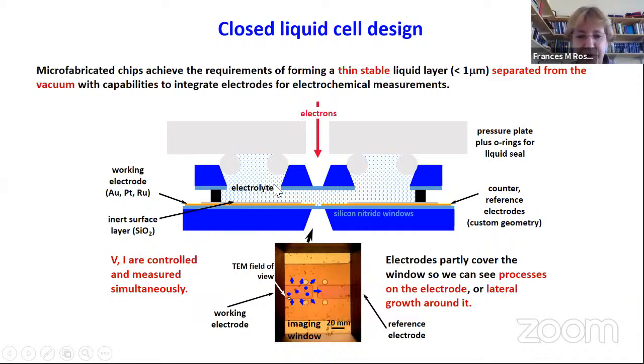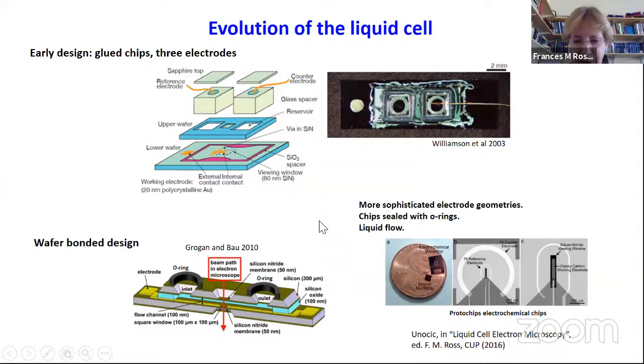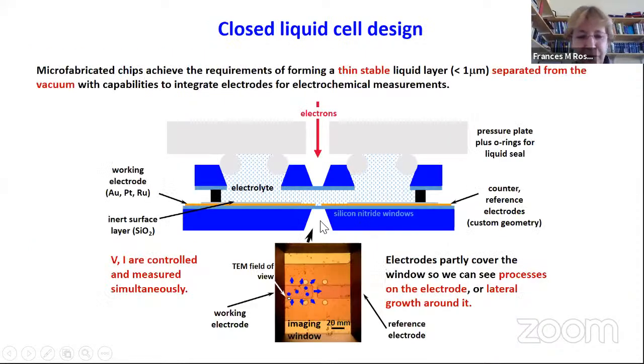And so we want to do electrochemistry. We have to put some electrodes, and we put them here on the bottom chip. They're made of stripes of gold in this case, or platinum or something, and they extend over the electron transparent window. So the path of the electrons is through the vacuum of the microscope, through the top window, through some layer of electrolyte, that's usually hundreds of nanometers, through an electrode, which has to be electron transparent, through the bottom window, and then back out to the microscope vacuum, and then to the projector lenses and the camera.